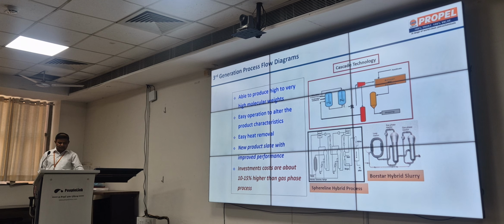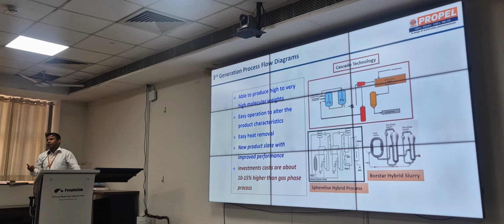Third generation process. In the third generation, we can produce multimodal grades, multimodal molecular weight distributions. In case of HDPE, when you are going for broad molecular weight distributions, you produce in one reactor a grade with an MFI up to 100. In fact, if you want to produce a multimodal grade for cap applications, in the first reactor you have to make the MFI up to 200, just like a wax material.